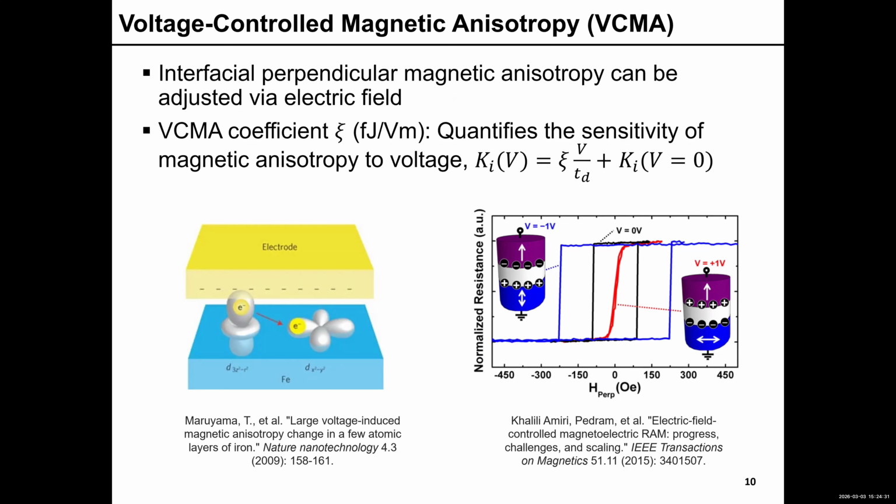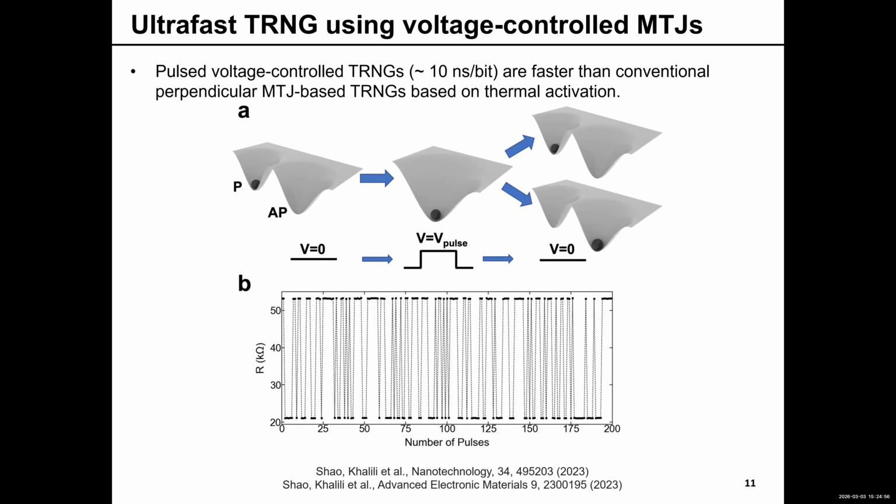And so what we learned from that is that it is not necessarily the case that a magnetic tunnel junction needs to be designed to be permanently stable or always stochastic. This is something that we can tune depending on need in a circuit. So we can really control the energy barrier depending on how we are using these magnetic tunnel junctions. And the idea is shown here, basically. You have essentially that same energy barrier that I was showing you in the previous slides.